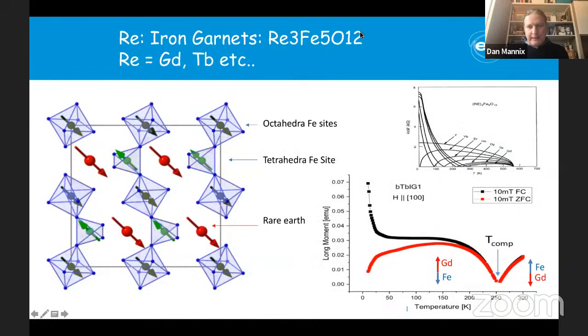If I talk a little bit about the magnetic properties of these iron garnet systems, these are ferrimagnetic systems, which means that they have antiferromagnetically coupled spins, but there's actually a net magnetic moment. The spins don't cancel each other out completely. So first of all, there are the iron sites. There are 2 iron sites in the gadolinium iron garnets. One is in an octahedral site, as shown here, and that is coupled antiferromagnetically with a tetrahedral site. So this is surrounded by oxygens in a tetrahedron. That gives a net iron moment, which couples antiferromagnetically with the gadolinium, or the rare earth.